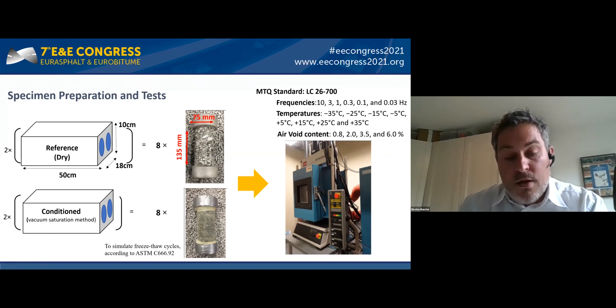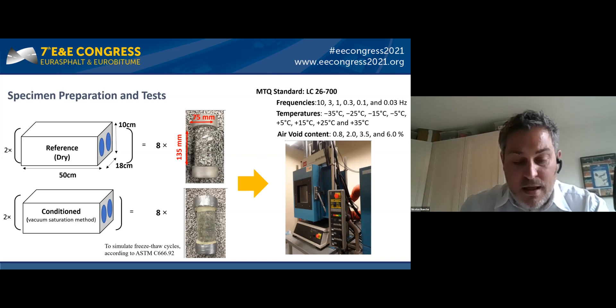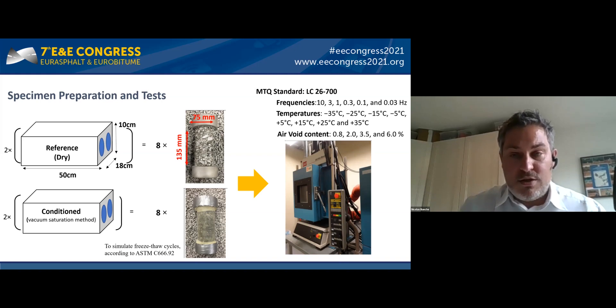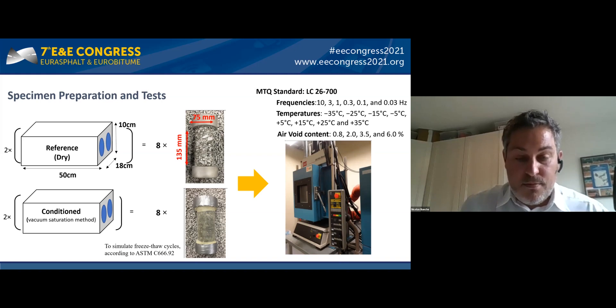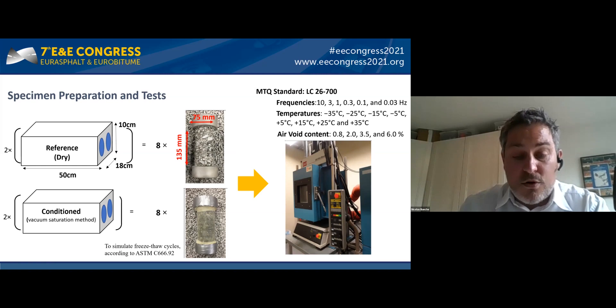The specimens were divided into two groups: a first reference group kept in air-dry conditions as control specimens, and a second group conditioned through vacuum saturation. After the saturation process, each conditioned sample was submitted to 150 and 300 freeze-thaw cycles as set forth in the ASTM standard test method for resistance of concrete to rapid freezing and thawing.